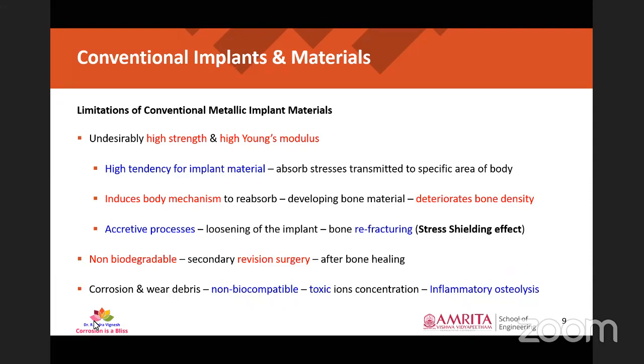Okay, and this will induce a body mechanism to reabsorb the developing bone material, which deteriorates the bone density of the developing bone. And this process, that is the tendency of implant material to absorb the stresses and the induction of body mechanism to reabsorb the developing bone material, will lead to loosening of the implant and bone refracturing. Okay, and this effect is called the stress shielding effect. So it is not desirable at all.